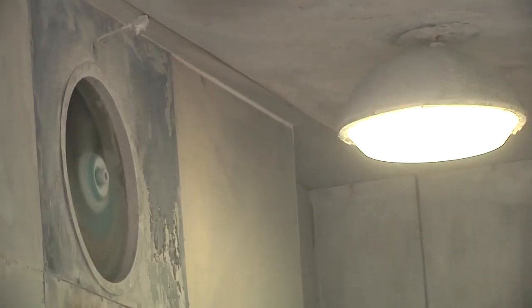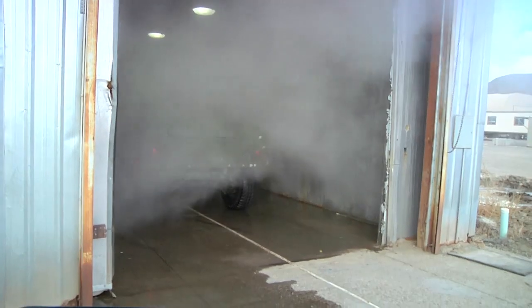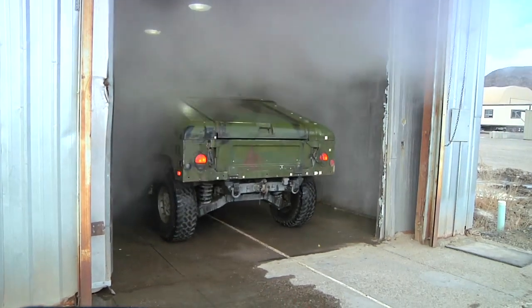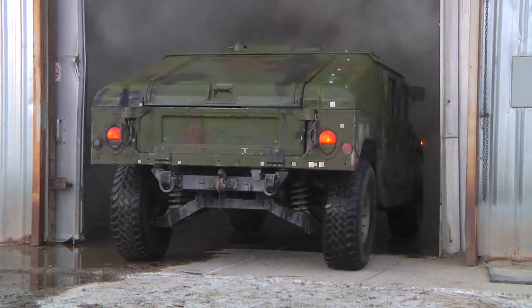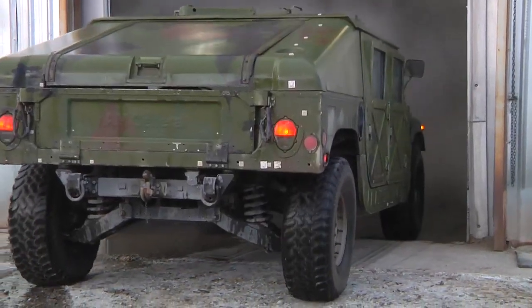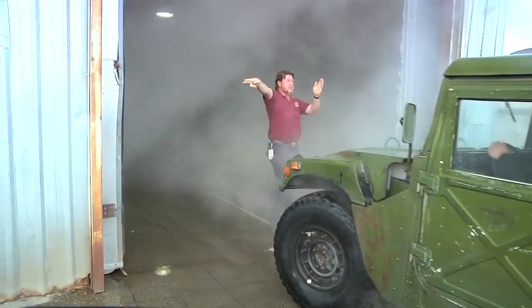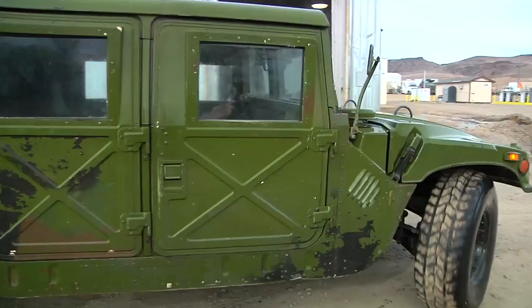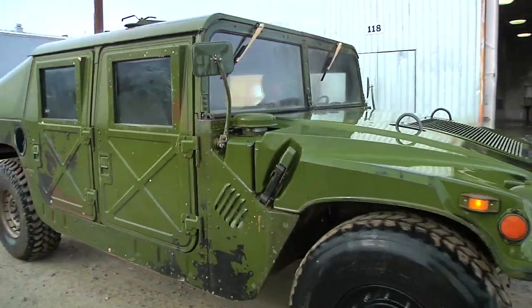But all of this still isn't enough to accelerate corrosion of these vehicles. What we need is humidity and lots of it. This is a high-temperature, wet, nasty environment, which is the workhorse of the vehicle corrosion test, the humidity chamber. A vehicle will soak in this environment for up to 8 hours a day at 140 degrees Fahrenheit and 100% humidity, which lets the corrosion process continue for longer than it would under normal conditions. These military vehicles undergo this daily barrage of testing 176 days straight to demonstrate that they can survive for 20 years in the military.